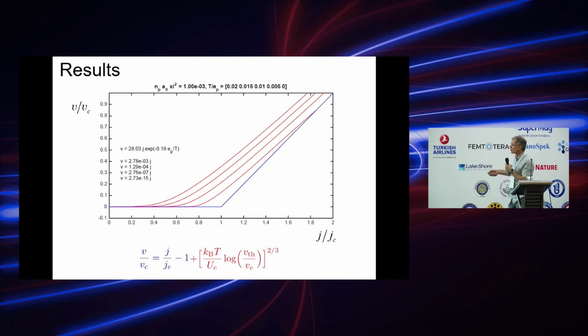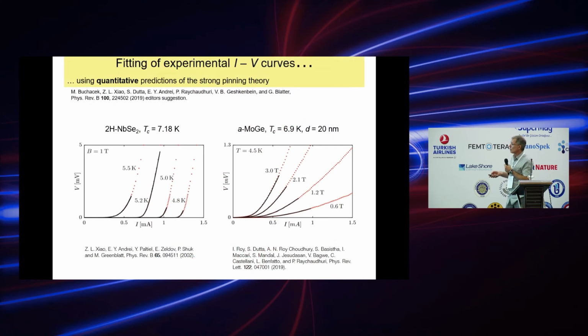So the most effect that you see with creep is the shift of the flux flow to lower temperature and appearance of curvature. To see the finite slope, you really have to zoom very strongly, so it's a much weaker effect. And then as you see, this curve looks pretty much similar to this curve, data of Kim and co-authors, and we try to compare it with more recent experiments.